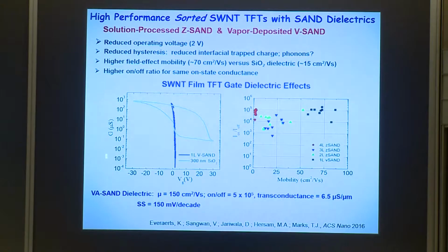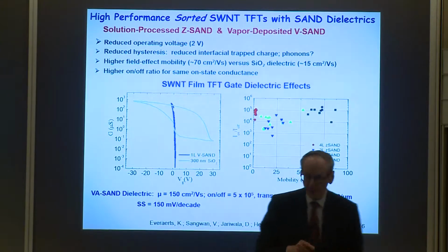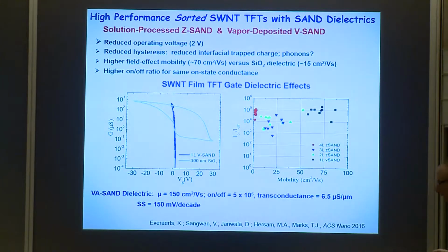And this is the transconductance, but think of it as the current versus the gate voltage: huge hysteresis. And that's bad, except if you want a memory device. That's trapped charge between the semiconductor and the dielectric. On the other hand, if I use SAND instead, look how crisp this turn on and turn off is. And the mobility is close to a record.